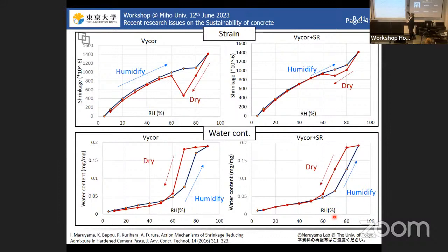The top figures show the strain, the length change isotherms, and the bottom figures show the sorption isotherms. So this is the Vycor glass, and this is the Vycor glass plus shrinkage reducing agent. And this is a very famous graph. In the desorption branch, we see the capillary shrinkage here. The general shrinkage is governed by the surface energy concept. And this shrinkage is coming from this desorption branch and the difference between the absorption and the desorption. And this additional condensed water makes this additional shrinkage.